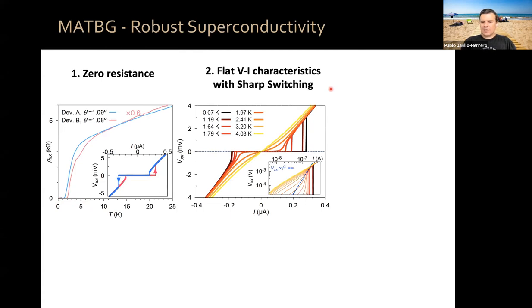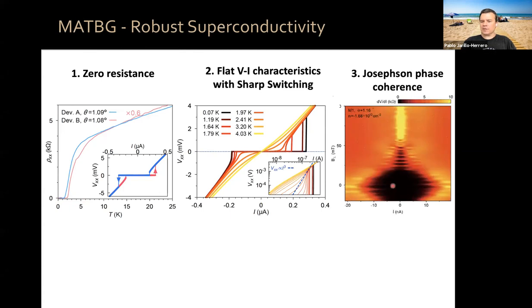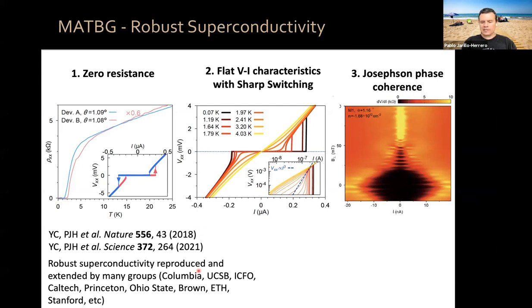And perhaps as importantly, if not most importantly, is the observation of Josephson phase coherence. If you apply a perpendicular magnetic field in a region of your device where you have superconducting islands coexisting with non-superconducting islands, you can observe Fraunhofer-like interference patterns of your critical current. That demonstrates that there is Josephson phase coherence, and this is the last thing that truly 100% confirms that this is a robust two-dimensional superconductor. I'm showing data from these papers here, but this robust superconductivity has been reproduced and extended by many, many groups nowadays.